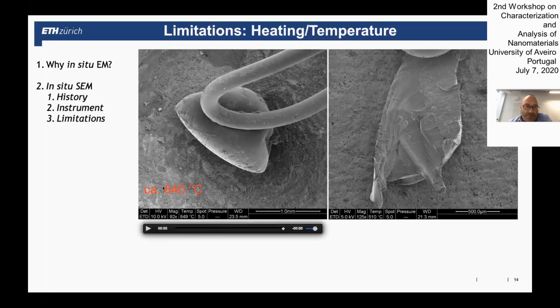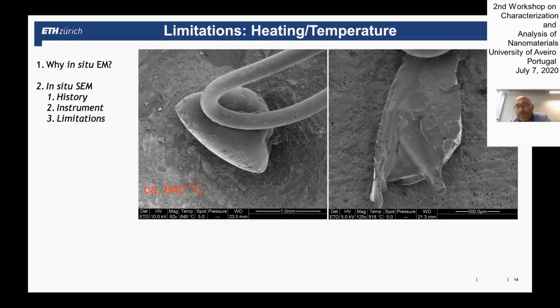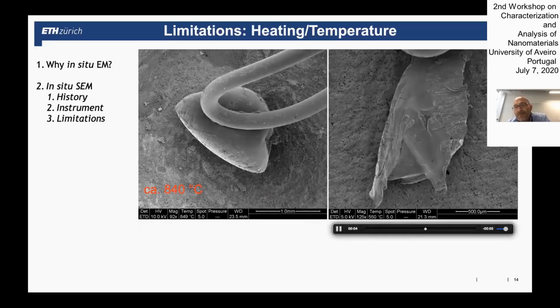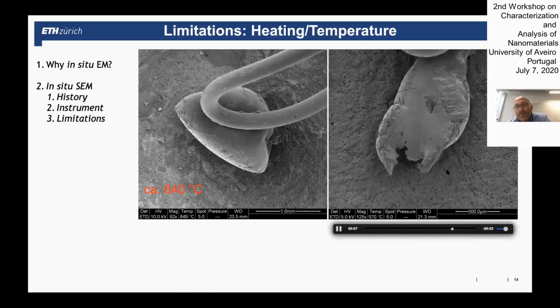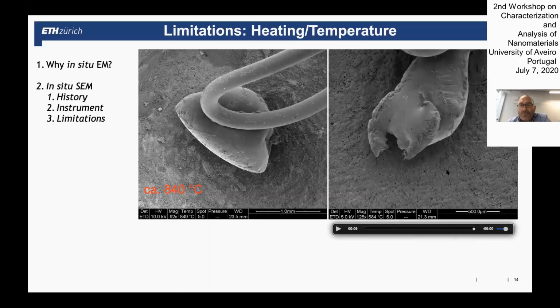So here we measured that the aluminum melts at 840 degrees C. You see that nicely in the video when it suddenly changes shape. That was at around 840 degrees C. And in the same aluminum, different experiment, again aluminum, different particle, we heated it again, and this time the thermocouple was mounted somehow differently. And in this experiment, it seemed to get liquid at 550 degrees C.